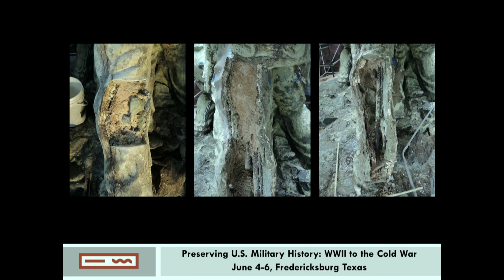This is the left leg of Ira Hayes at the back, one of the worst areas. So you can see on the left of the slide, opening up that area. Gradually, the clay was removed in the center image, revealing broken and corroded rebar in the third image. I should also point out that when we opened this part of the leg, near the foot, water actually flowed out from being trapped inside, like gushed out. It was kind of insane how wet it actually was.